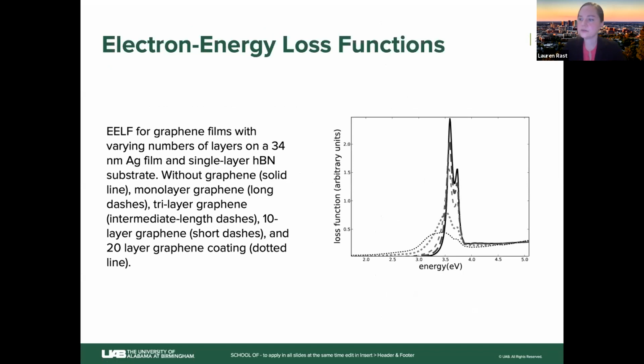Okay, so this shows graphene films for varying numbers of layers on a 34 nanometer silver film and a single layer hexagonal boron nitride substrate. Without graphene is the solid line, a single layer of graphene is the long dashes, 3 layers is the intermediate dashes, 10 is the short dashes, and 20 is the dotted line.